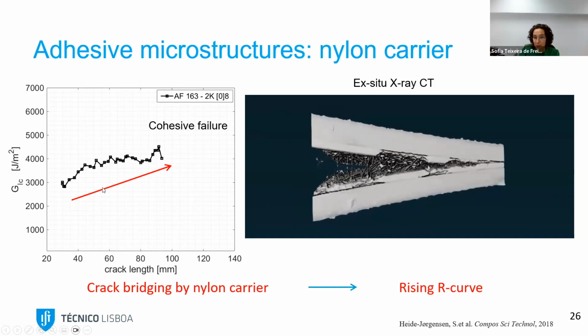So this is great. However, this happened only by chance, because this nylon carrier was not put there to do the crack bridging. It's there just for manufacturing purposes. So this is just by pure luck that we saw this phenomenon. But it triggers us to try to use this phenomenon to our advantage and control the phenomenon without relying only on luck.